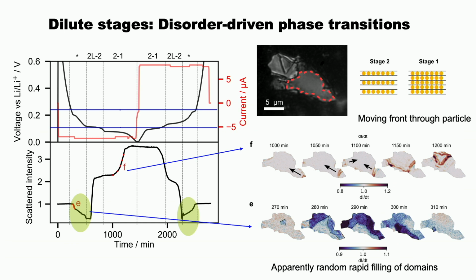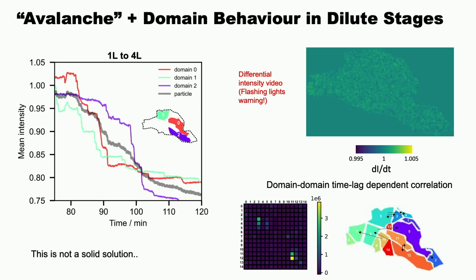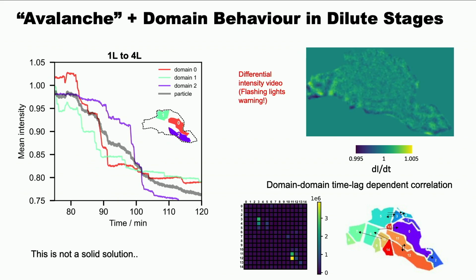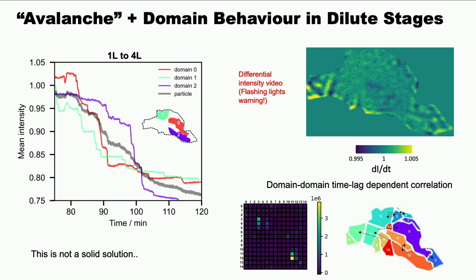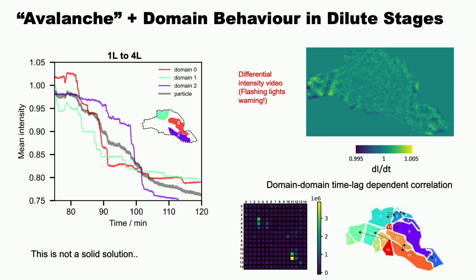And if you look at the individual domains, you can actually see that there are domains being lithiated semi-randomly and continuously. So if you're epileptic, please look away in the next image, because this is what's known as a differential image, and it's flashing. And so this is the domain in the first stages, and you're seeing these events of different layers looking as if they're almost uncorrelated as the different layers are being filled. And you can track the correlations between them, and there's definitely relationships with one following another. But if you look at the intensities, it's not a smooth, solid solution as the electrochemical profile would suggest. It's these little series of steps.